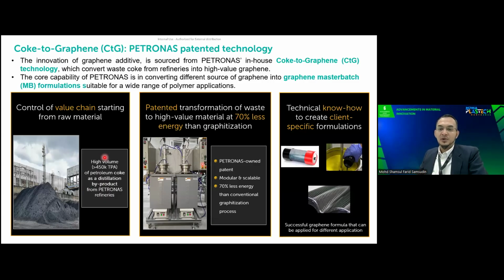For the coke, normally the price is around $200 per ton. So when we convert it into graphene, we can add more value and generate more income as a special type of additive. And the beauty of this technology for graphene synthesis is that we have a patented technology where we produce our graphene using a modular reactor. The good thing about this modular reactor that we developed is that it uses 70% less energy compared to the conventional technology outside, which requires very high temperature to convert petroleum coke or graphite into graphene. And we also have the technical capability to produce this graphene as an additive for different applications.